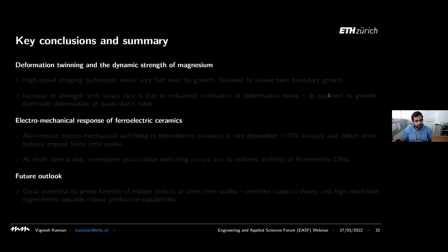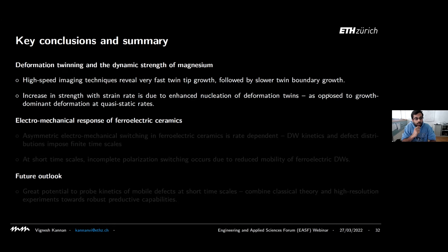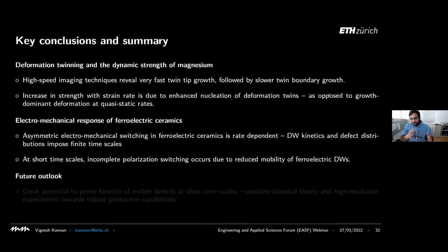And I hope I've convinced you that looking at non-equilibrium material response, especially at short length and time scales simultaneously, is very useful both for science, of course, but also for engineering applications. We looked at an example from deformation twinning where we use high-speed imaging techniques to look at these interfacial kinetics. We observed that the increase in strength is coupled to a transition from a growth-dominant mechanism to nucleation-dominant mechanism. We then took these ideas to ferroelectric ceramics, which involve electromechanical coupling.